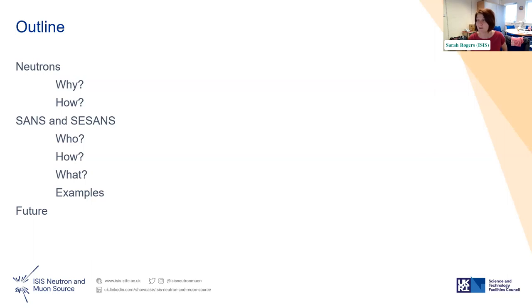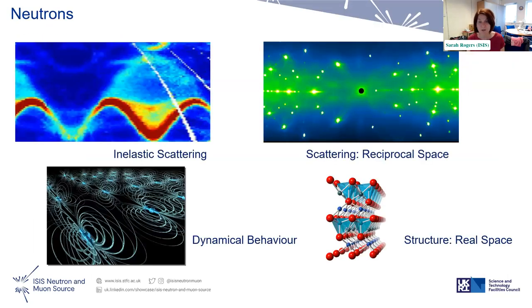But of course, I don't have a crystal ball, so it's always difficult to know for sure where we're going. So neutrons, I'm sure you're probably aware, we do inelastic scattering to probe dynamical behavior, so to look at how atoms and molecules move. And then we do scattering in reciprocal space, and that gives us information about structure, which we convert then to real space structure.